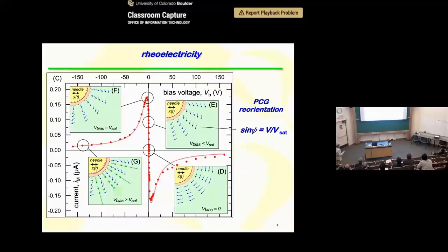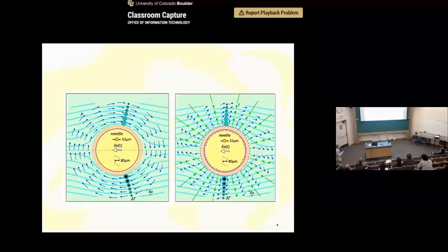I'll just get to the bottom line here because I wanted to get to the application part before time runs out. So what happens is when you put the needle in, in the vicinity of the needle, the ferroelectric nematic organizes into this sort of circular texture around, which you can control by applying a voltage. So you can change the angle of the polarization relative to the needle, and that enables you to tune this effect.